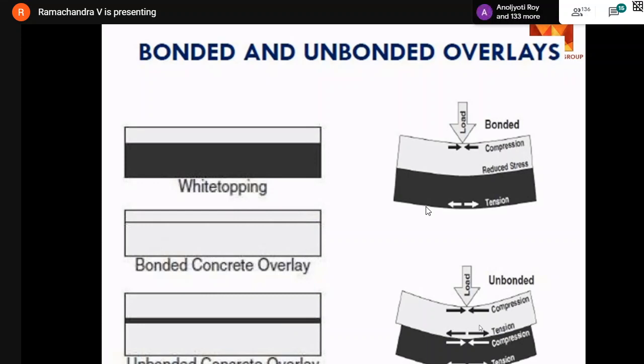There is no need actually. If you directly put concrete over the milled bitumen surface, there is some roughness of the surface. Therefore, there is always some amount of bonding between concrete and bitumen. Now, if there is bonding, what happens? Tension comes at the bottom. That means bitumen can take up tension because it is a flexible material, and compression concrete can definitely take.